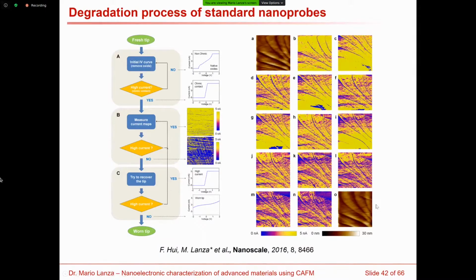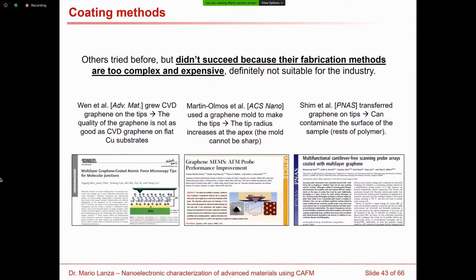So my idea was to take the AFM tip and coat it with a flake of graphene because it is mechanically stable and highly conductive. And I checked the literature at that time, and there were some approaches that were being used. The first one was to grow the material directly on a metal-coated tip. However, this involved temperatures of up to 1000 degrees, which means that the metallic varnish is going to melt, and it didn't give very good results. The second one consisted of making a kind of mold of copper covered with graphene, and then injecting some photoresist in order to make the tip, and at the end etching the mold. However, these produce tips that are not very sharp.